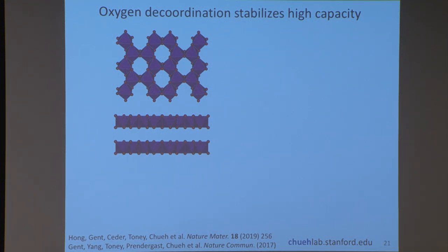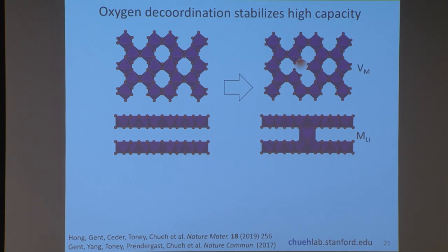This is the pristine material. With all of the lithium removed, this is the top view and the side view. You have the van der Waals gap here that has no lithium. And here is what happens when one of those metal atoms decides not to stay in the metal layer, but rather moves down to the lithium layer. This creates two defects in the material. One, you're missing a metal atom in the metal layer, and two, you now have an extra atom in the lithium layer. We call this a metal vacancy and a metal antisite. And the formation of this pair leads to a substantial change in the chemistry of the metal-oxygen bond.